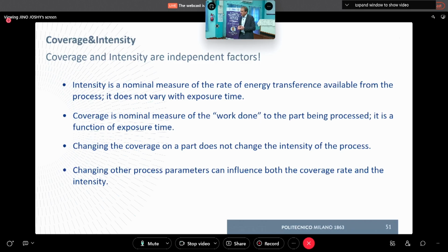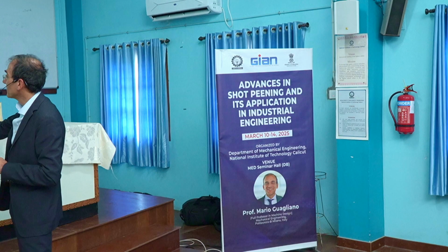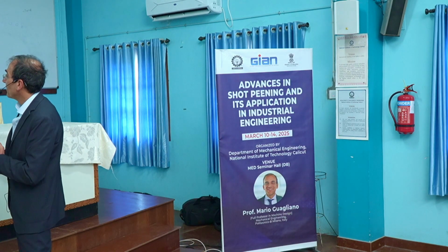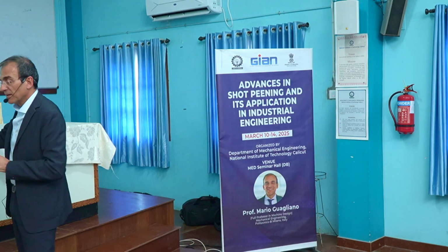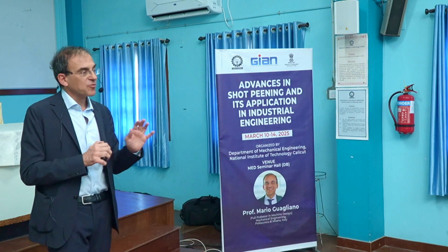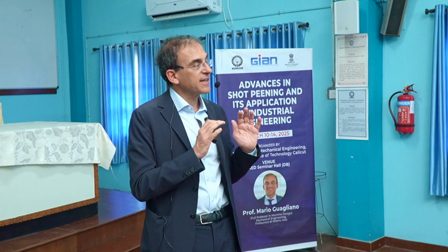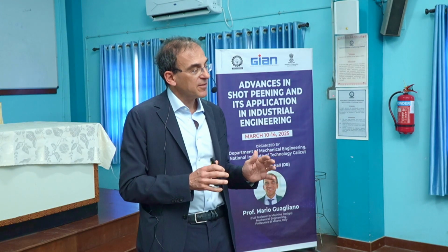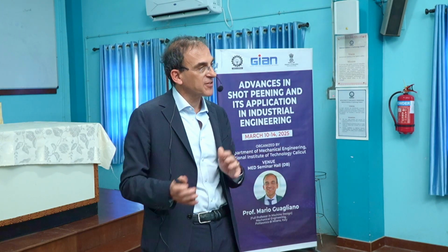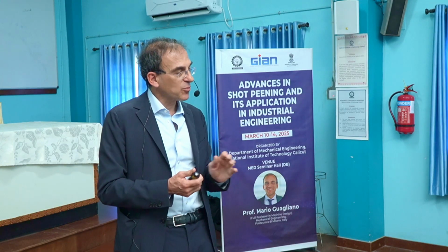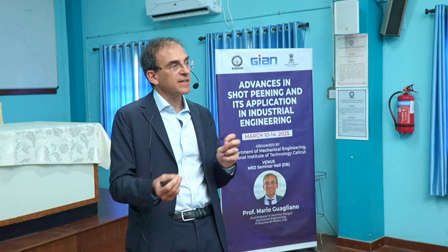And finally, let's remind something about coverage and intensity. Because sometimes these two concepts are confused, but they are independent factors, and are independently checked. There is no way to consider coverage as something related to intensity.